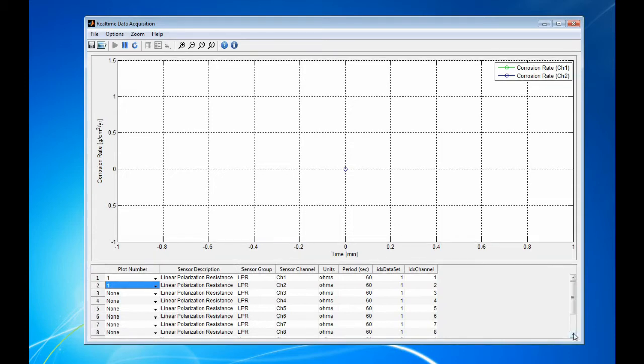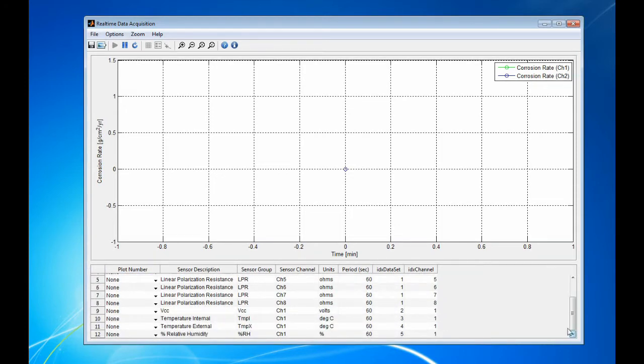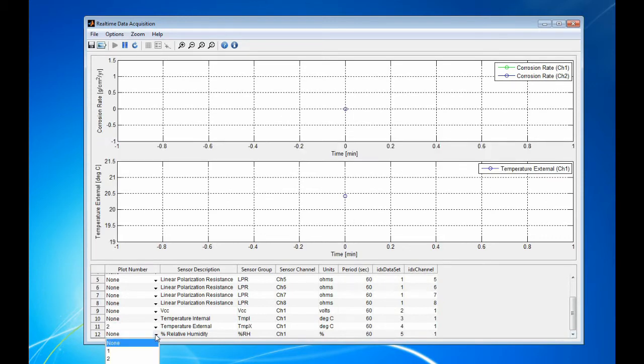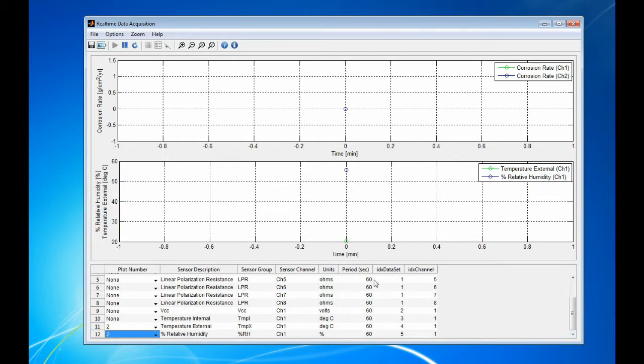Typically, in a dry condition such as it is now, the corrosion rates under both sensors will be 0. And for environmental information, I'm going to add the external temperature. We'll put that in graph 2, and the relative humidity, which is measured in the presence of the sensors. So here in the room, the relative humidity is approximately about 56%, and the temperature is about 20 degrees C. Again, the corrosion rates are 0.